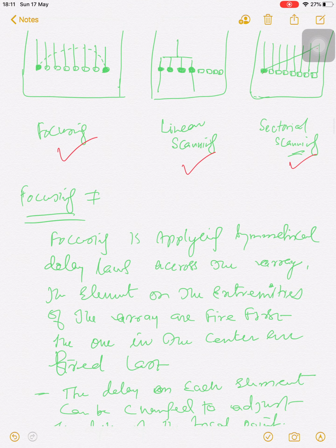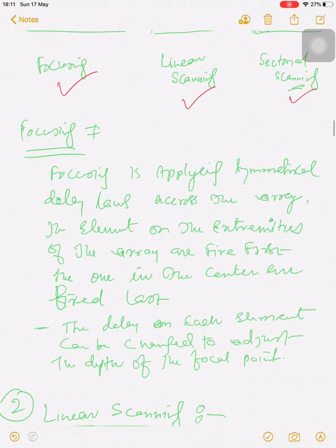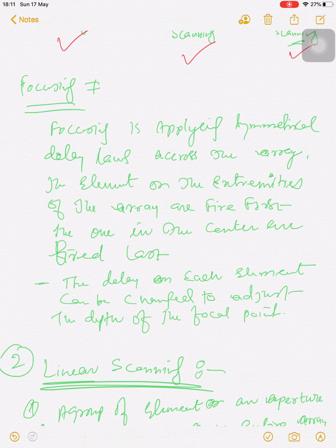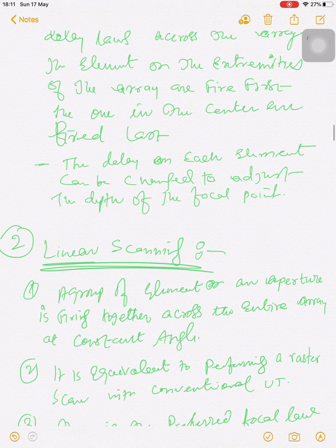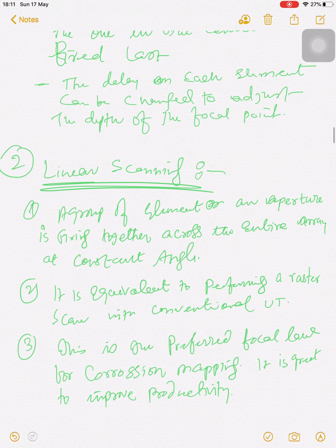Okay. Focusing is applying a symmetrical delay law across the array. The elements on the extremes of the array fire first, and the one in the center fires last. The delay on each element can be changed to adjust the depth of the focal point.